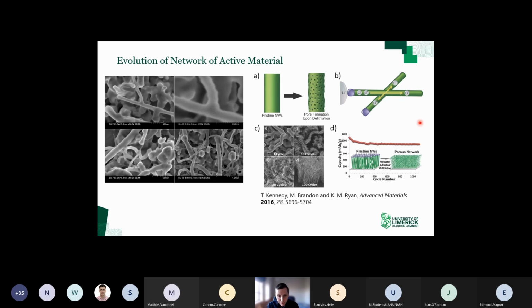The welding occurs because if you have 2 ligaments in contact with one another, both of them can be lithiated simultaneously, and you can get a lithium bridge bonding between the 2 ligaments. When that lithium is discharged or delithiates, it is removed, and so there's a kinetic driving force for silicon-silicon or germanium-germanium bond formation at the interface of the 2 ligaments. So you get welding and pore formation, and both are critical to form that very stable porous structure.